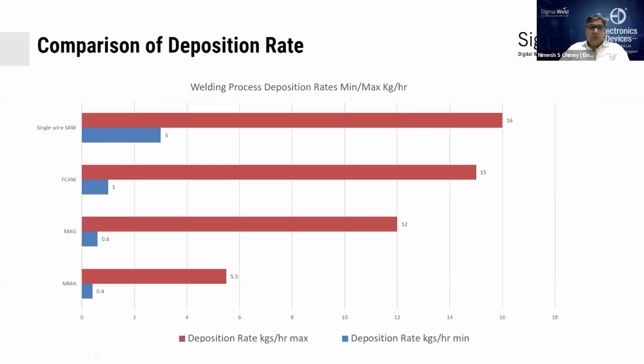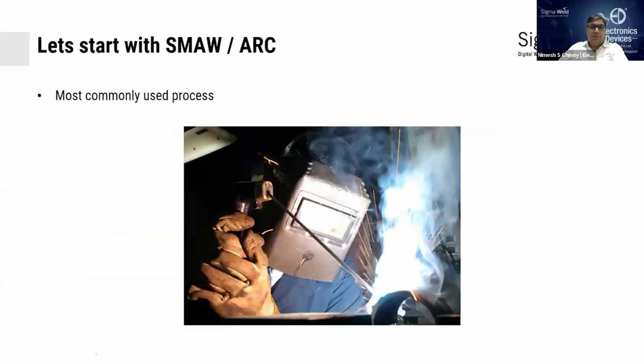So here's a small chart which shows you a comparison between deposit rates for arc welding, which is right at the bottom, about 400 grams to 5.5 kgs per hour. And then you have MIG-MAG, which is at 600 grams to a max of about 12 kgs. Then you have flux core, which is about 1 kg per hour to a range of about 15. And single wire submerged arc, which starts from 3 kgs per hour and can go up to 16 kgs per hour. Of course, there are variants in submerged arc which can take it even higher. But for the sake of our discussion, this will be good enough.